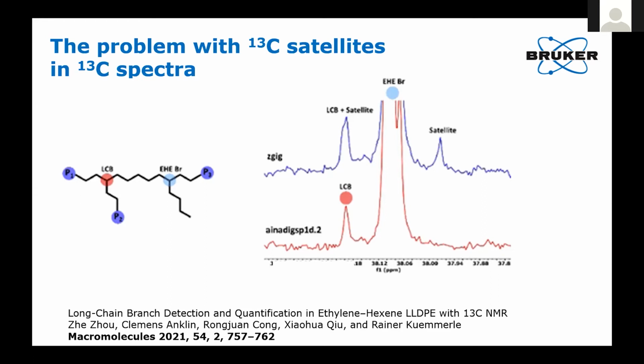Another signal which can affect the detection of low-level peaks you want to look at, here a branch point in a linear low-density polyethylene. We see that the peak of interest is actually overlapped with the carbon satellite. And the question was how to get rid of this.